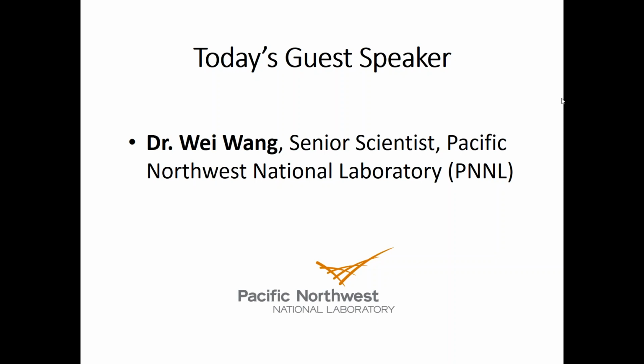So what I want to say is, for the low temperature electrolyte, this is something we can research and develop. Previous research went more or less towards the high temperature side because of the vanadium 5 precipitation issue, but on the low temperature side, the solubility of the salt can be adjusted by concentration or by different combinations of the ions inside the electrolyte. So that's something we can work on. But judging from what Uni Energy has announced in their system, I think minus 30 is already a very good system